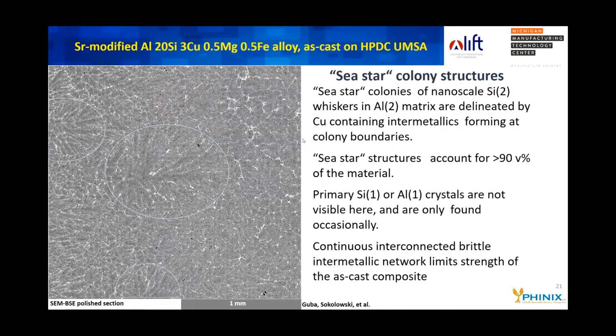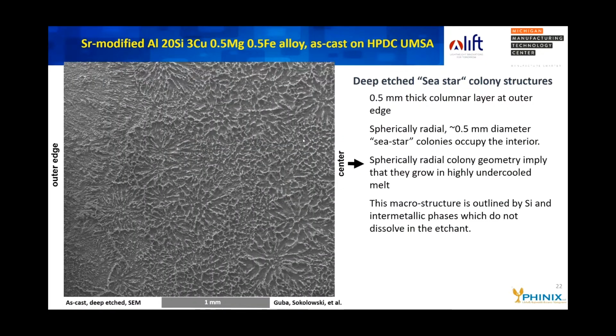One would think that the interconnected continuous brittle network would be bad news, because in this form, as-cast, it limits the strength of the as-cast composite. Now we deep etched the material to reveal a little bit more of the structure. And again, you can see that the intermetallics are now standing proud of the surface and really show up the microstructure.